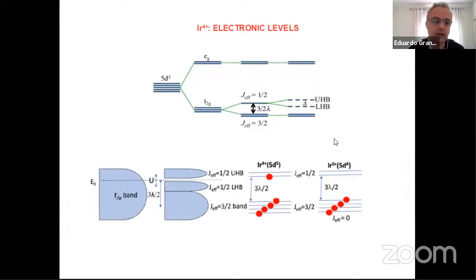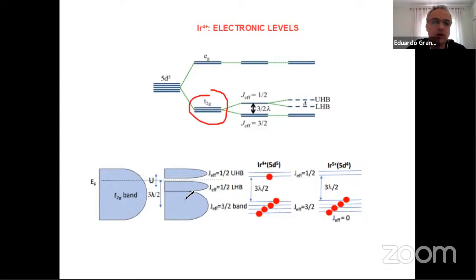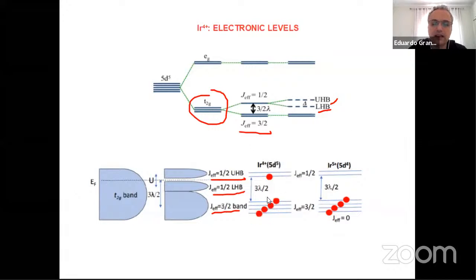If you look more in terms of bands instead of atomic levels, which is actually the case, instead of these discrete levels we have a band, the t2g band, like this. So we have this t2g level in the atomic description, which in the solid description becomes a t2g band. And this t2g band splits into the J_eff equal 3/2 band, which is related to this atomic level, and then the J_eff equal 1/2 lower Hubbard band and upper Hubbard band, which are related to these levels if you look just at the atomic levels. And then we have this occupied by 5 electrons, so that's what is mentioned here for the iridium 4+ ions which we are interested in. So that's the physics.